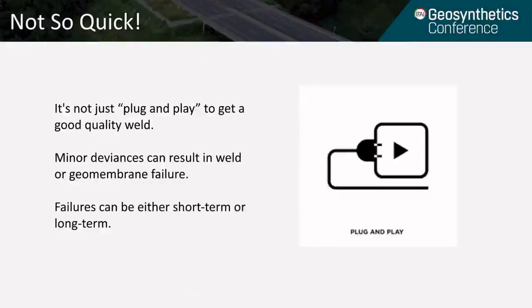Unfortunately, our industry often looks at welding as a plug and play, where all you have to do is get your welding machine, put the liner in, let it run, and you're going to get a good quality weld. Well, that's not the case. Minor deviances in either heat, speed, or pressure can result in significant geomembrane failures. And those failures could be short-term, where they'll be obvious during construction, or they could be long-term, where they may degrade over time because of improper welding and fail 5 to 10 years down the road under stress.